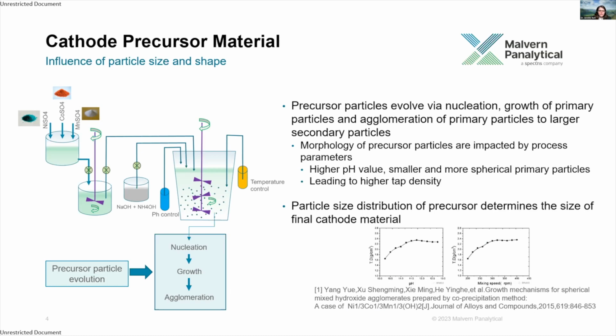So the precursor particles will evolve by nucleation and grow into primary particles. And then these primary particles will agglomerate together to form larger secondary particles. The size and shape of those particles are impacted by the process parameters. So if you increase the pH, you tend to get smaller and more spherical primary particles being produced. Similarly, increasing the mixing speed has a similar effect as well.